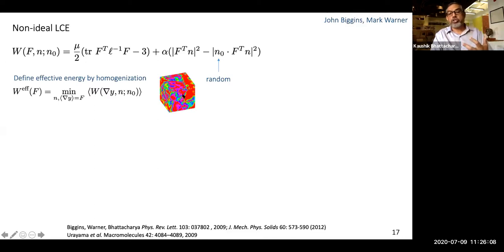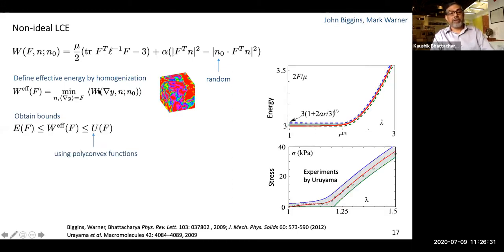So what I can try to do is to compute at least the homogenization of it, the effective behavior. So I take a box of this material, I impose an average shape, and I calculate the minimum of the average energy. Of course, I can't compute this explicitly. So one thing I could do is to compute bounds. And alpha equals 0 gives you one bound. And then, of course, you have the other bound. You have to do some theory.